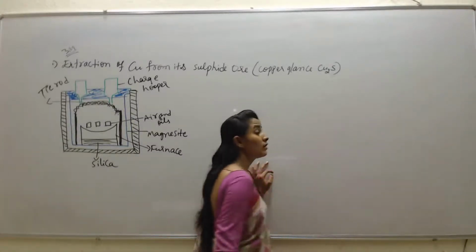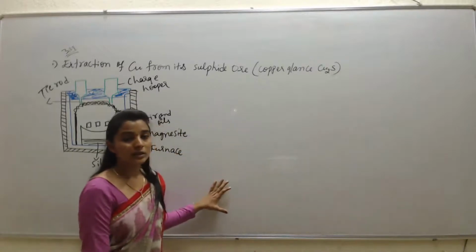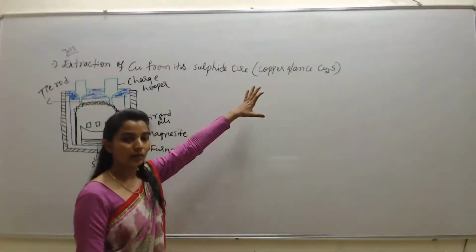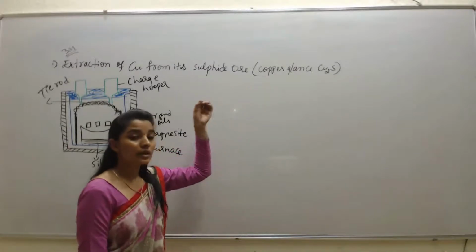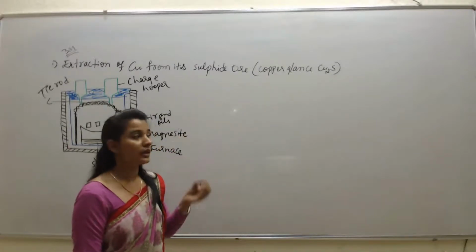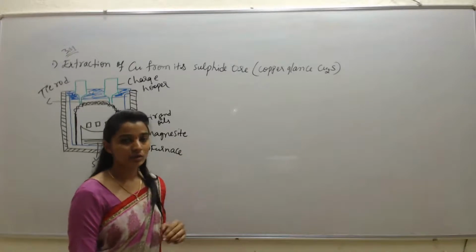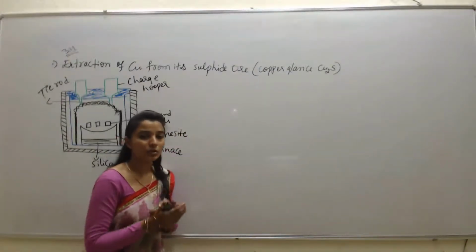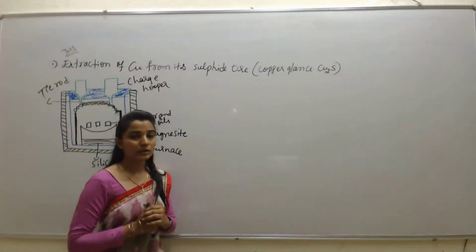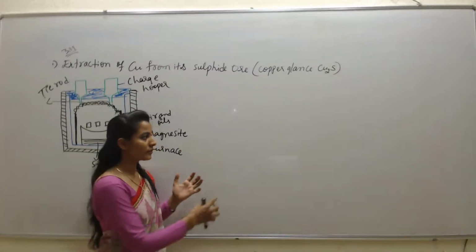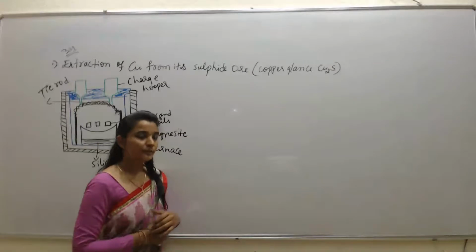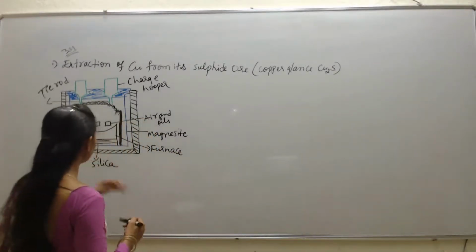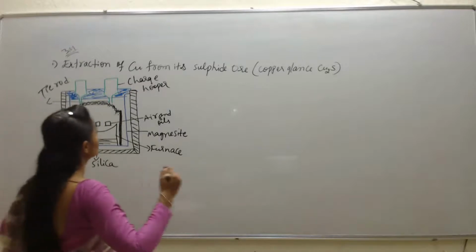Once it is converted to oxide ore, in the Ellingham diagram, the copper oxide ore is at the topmost of the series. In the Ellingham diagram, it is at the topmost curve. Okay, so that means even if we choose any of the metals, it can have the ability to reduce the copper. At the same time, for better results, we choose only carbon to reduce other metals because it easily forms CO2, that is a gas that easily escapes. Okay, so listen, here what happens?